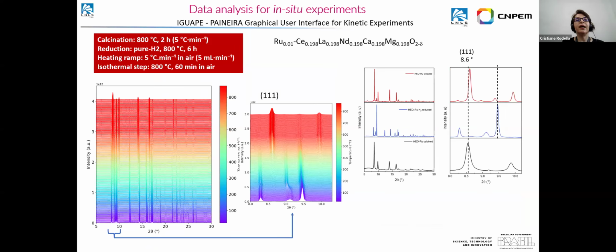Another example that I'm going to show here was a very complex, high entropy material, and the idea was first to see if the doping of this material formed a new structure. The experiment was performed at Paineira. And here are all the diffractograms that were obtained during the experiment.